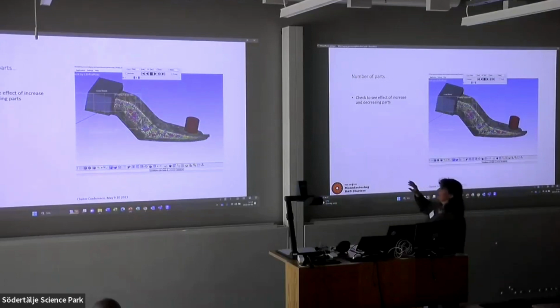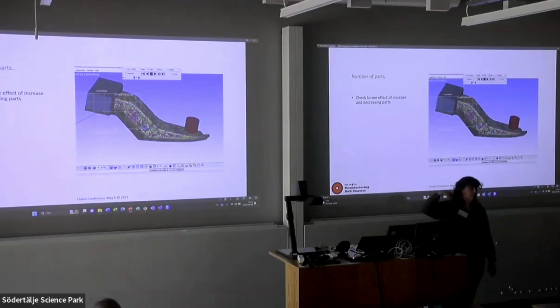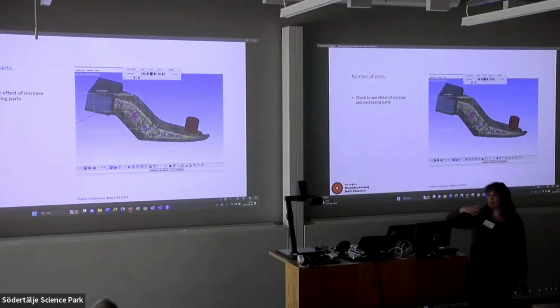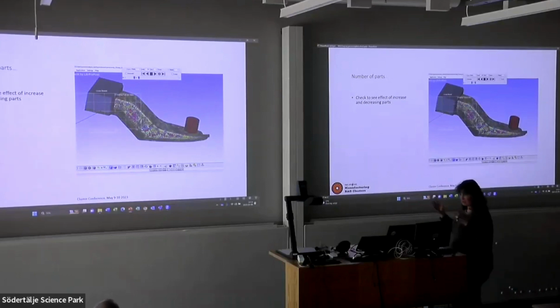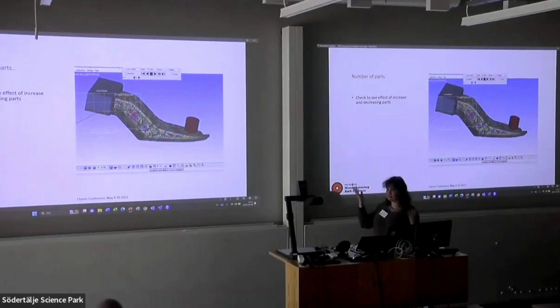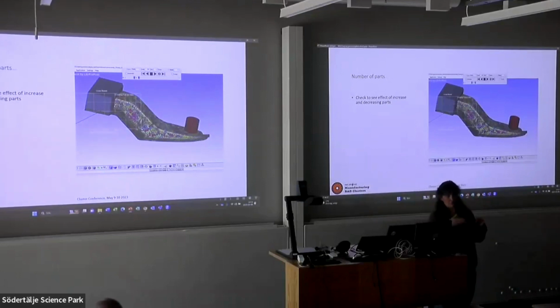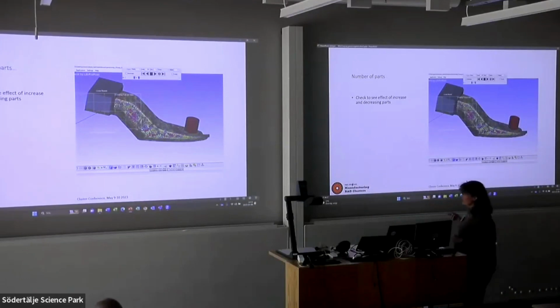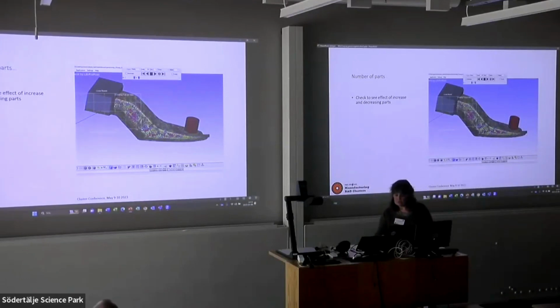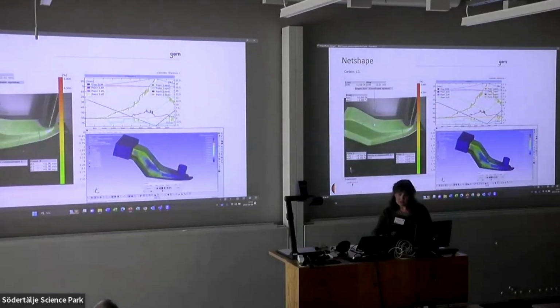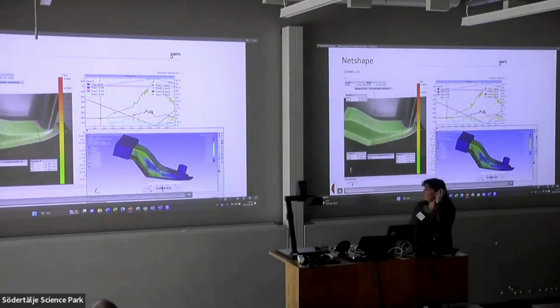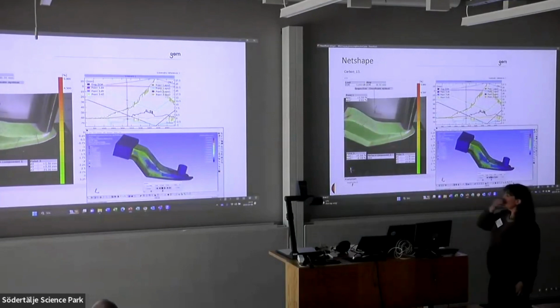And the number of parts used here is 10, but you need to check to see when is a good number of parts to use. It will depend on the application and on the materials used. 3 could be enough, 20 might be needed. But at this stage, 10 was the one where we didn't see much difference. We were looking at the stiffness and we didn't see much change in the stiffness. So this is what we're then using to compare against the actual test.